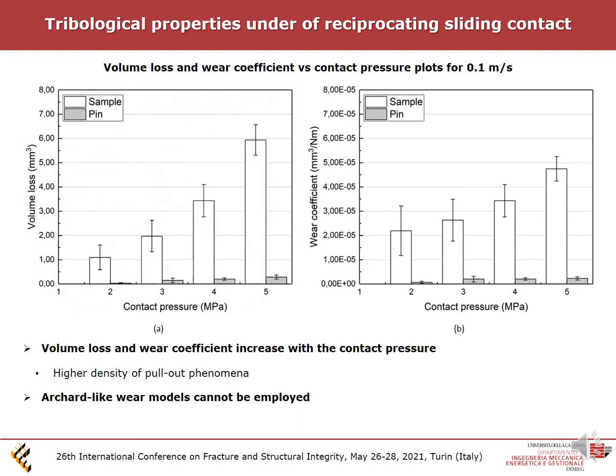In addition, the evolution of volume loss and wear coefficient as a function of the contact pressure, shown in this slide, indicates how both volume loss and wear coefficient tend to increase with increasing contact pressure, as a consequence of the higher density of pull-out phenomena, as confirmed by the microscopic observations. This evidence, in fact, suggests how, in this case, Archard-like wear models cannot be employed.